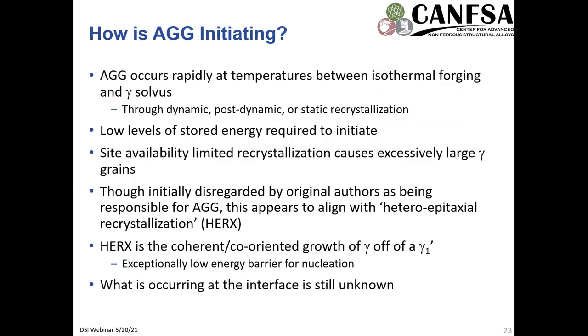And so really what we're interested in, we've seen the growth stages of abnormal grain growth, and we're trying to get a grasp at how this is initiating. What's the initiation of these recrystallization nuclei? This has been demonstrated to occur rapidly at these temperatures, specifically between isothermal forging temperature and the gamma prime solvus. And we've demonstrated through various experiments that this can occur through dynamic, post-dynamic, or static recrystallization, though the differences between post-dynamic or metadynamic, as some call it, and static recrystallization is really kind of semantics. There's not too much in terms of mechanisms there that are different, but I'm just listing those three out for clarity. And it has been demonstrated to occur at low levels of stored energy that are required to initiate. So it appears that there's a different mechanism rather than traditional recrystallization that's occurring here, and this is what we're trying to explore.